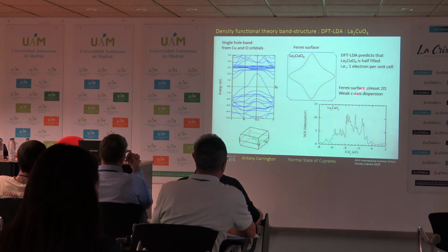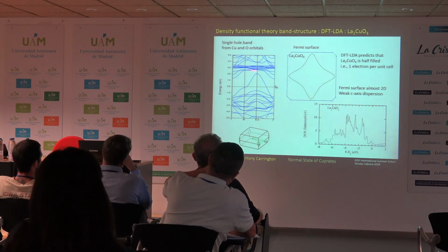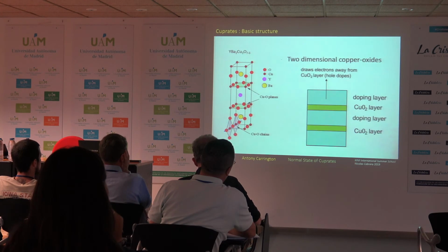If you did density functional theory on lanthanum copper oxide, what you would find is that it's a metal. There's a single band, this hybridized oxygen and copper band that's hole-like, and a single band passes through the Fermi level, and then you get a bunch of other stuff here and here that's away from the Fermi level. The Fermi surface is basically two-dimensional, because if you look back at the structure, you can easily make electrons move in this direction, but they're very hard to move in this direction, so it's two-dimensional.